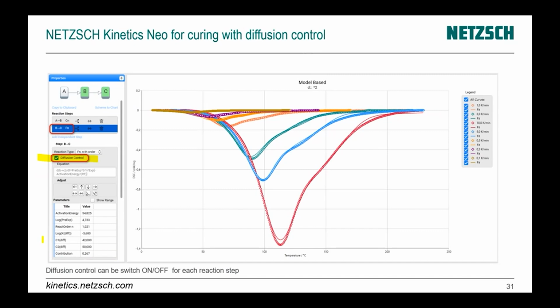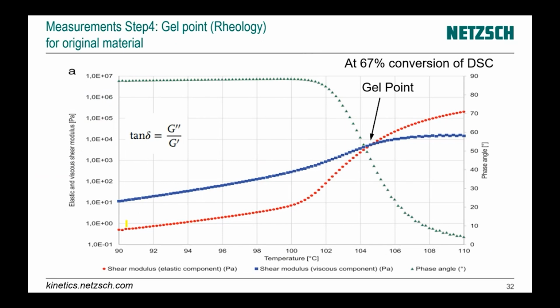And after optimization, we have these values C1, C2, and the initial value of the diffusion factor, which are found for the best fit between our model and our experimental data. Now we have this data, and we can start to make the time temperature transformation diagram.